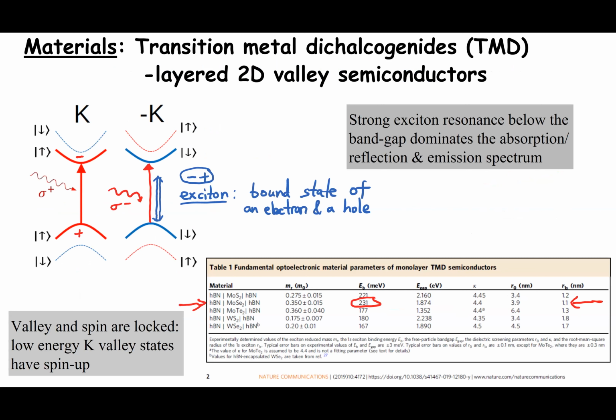Now, in the TMDs, transition metal dichalcogenides, I already told you that the band structure is like this, that we have a direct band gap at the K and minus K, or K prime, points of the Brillouin zone. The optical selection rules are that each valley responds to light with a well-defined polarization. This has to do with the circulation of the electrons being opposite in these two valleys. The main point is that if we extend the picture that I've shown you before, instead of having band-to-band transitions, when we shine light onto the system there will be resonances below the quasi-particle gap. And these are the excitons, the bound state of the electron in the conduction band to the hole in the valence band.